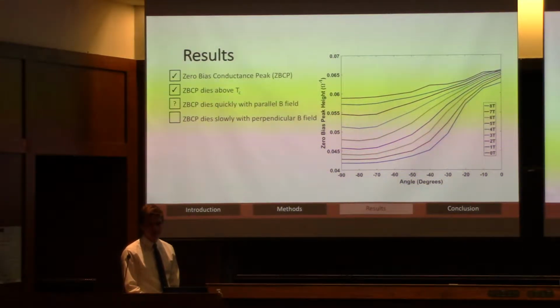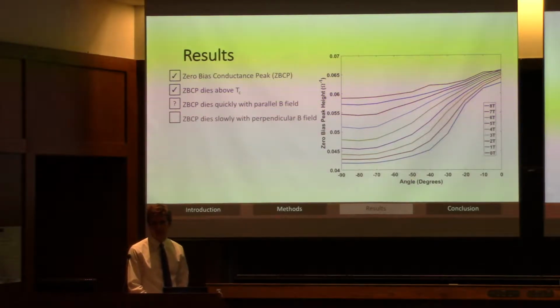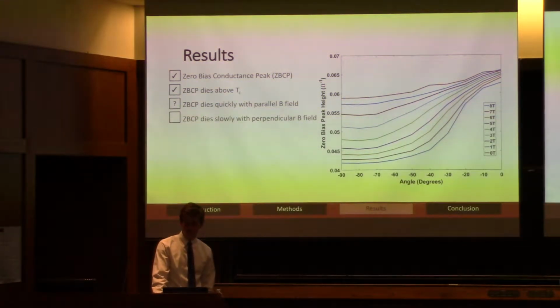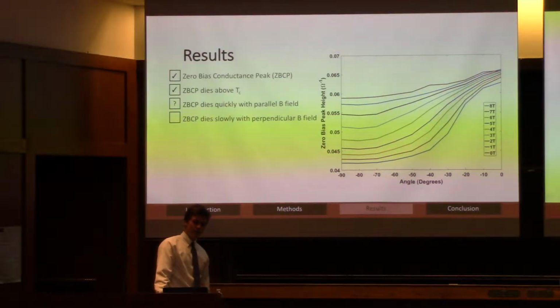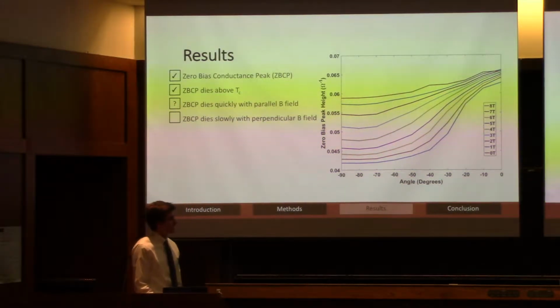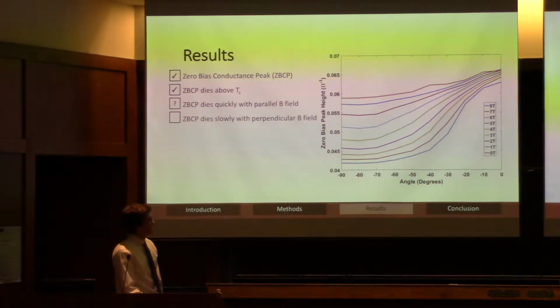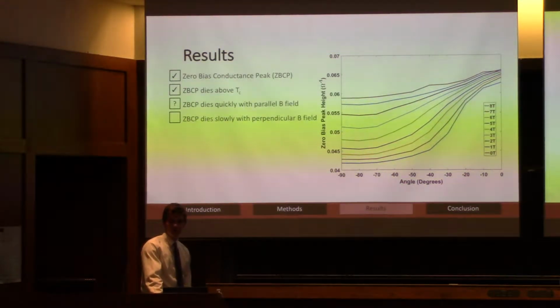Just to give you an idea, 8 Tesla is 160,000 times the value of the Earth's magnetic field. And that's increasing magnetic field as you go down here. So 8 Tesla is on the bottom. And at 90 degrees, you can see that peak dies. At 0 degrees, the heights are pretty similar, so magnetic field has very little effect on the height of that peak, but it has a really big effect out at 90 degrees.